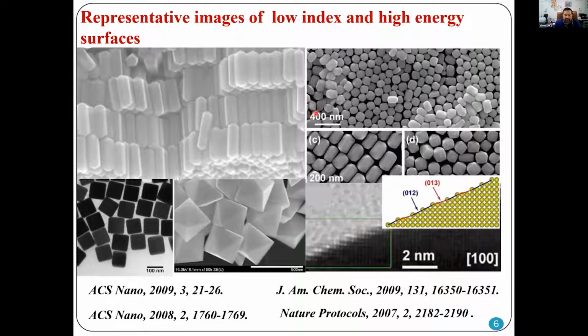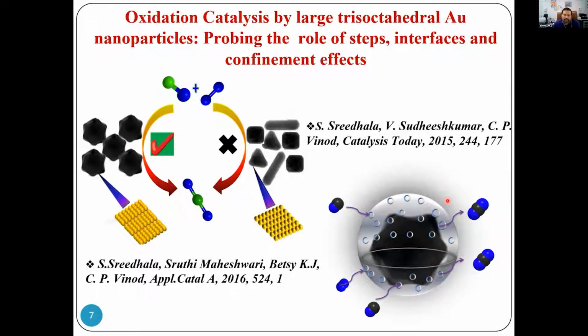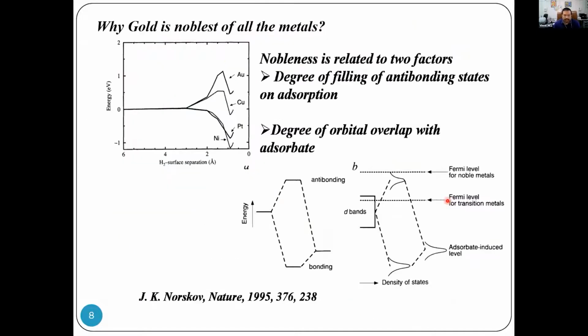These are some of the representative TEM images which I have taken from literature. These are typically from low index faceted nanoparticles like an octahedron or a cube shaped particle. You can also have high index faceted nanoparticles which expose these defective atoms on the surface. So taking this as a background, we started looking at carbon monoxide oxidation on gold nanoparticles. The reason this has been important is that gold is a metal which shows strong size dependence. Those who are interested in the chemistry of gold are advised to look at this particular paper, published by Nørskov in 1995, where he nicely talks, using density functional theory calculations, about why gold has a different kind of activation barrier for molecules compared to the other transition metals regularly employed for catalysis in the lab.